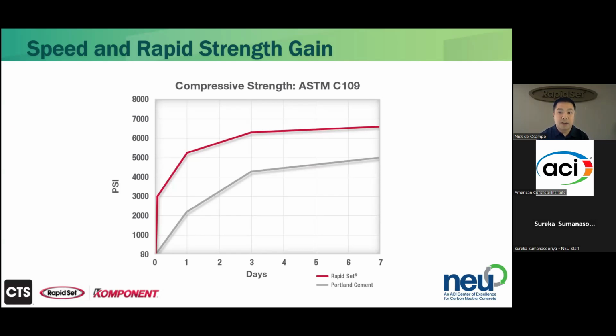But I do want to point out that after the first 72 hours, it has the same steady strength gain over time that more or less parallels that of Portland cement. And that is because of the presence of belite, which is the mechanism for strength gain for both products. So there basically is no strength regression or drop off over time with rapid set cement, with CSA belite cement.